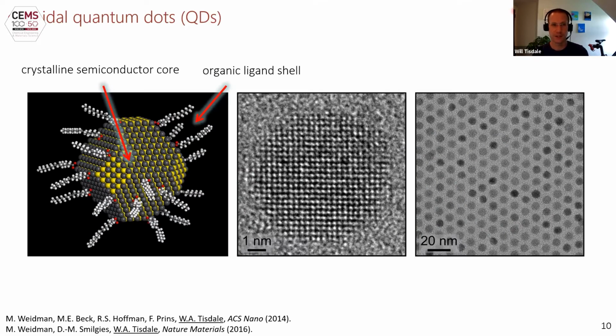They're synthesized via solution phase wet chemistry processes. And as a byproduct of their synthesis, the surface of these nanocrystals is coated with a layer of organic ligands. These ligands are essential to the processing of these nanocrystals because that's what imparts colloidal stability to these particles. If these ligands weren't there, the nanocrystals would aggregate in solution and flocculate out. The surface ligands also provide a handle for us for controlling the functionality of these materials and tuning the electronic